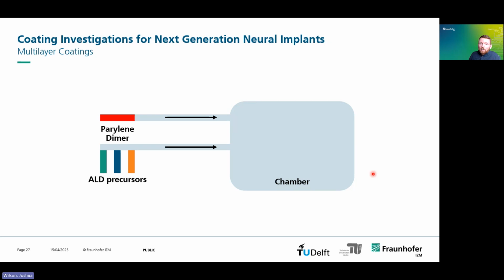Another additional advantage of the Parylene deposition is that it's possible to combine it with other deposition techniques which are deposited in vacuum. So this allows you to create multi-layered, truly conformal coatings with pristine interfaces, because if you don't break the vacuum of the chamber, the surface is going to be perfectly clean, and the cleanness is really of major importance when you want to ensure that you don't have delamination or defects between your layers.